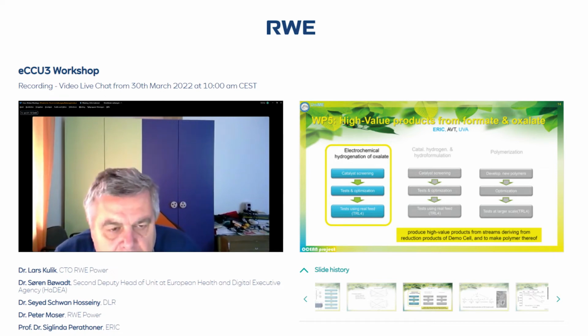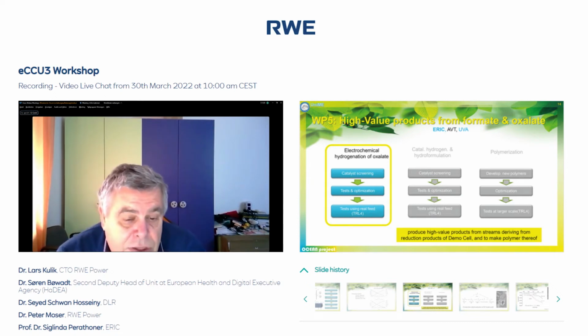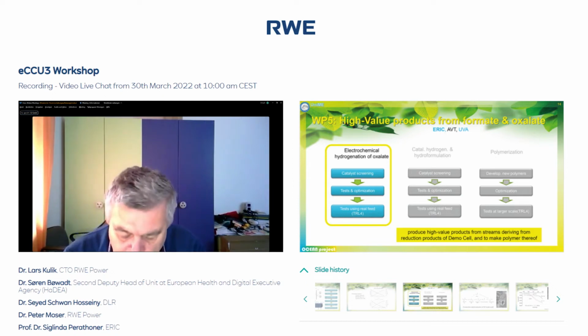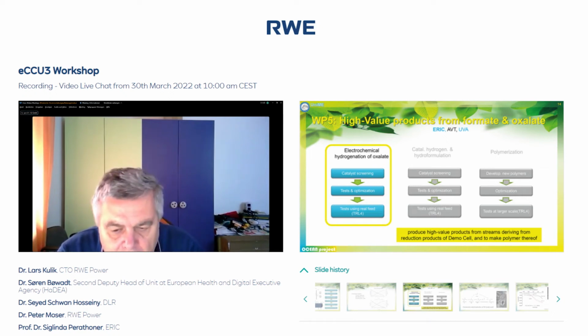The next one, number 14. The last part is dedicated to developing the electrochemical hydrogenation of oxalate. Here we were starting from essentially very minimal data in the literature, so we started from screening of the catalyst, then optimization, and finally we are now testing the real feed and also testing stability up to TRL4. Mainly this activity was on the academic side. Here is the reaction of oxalic acid. You see that you have a multi-step reduction to glyoxylic acid, glycolic acid, and then if you continue, to ethylene glycol.